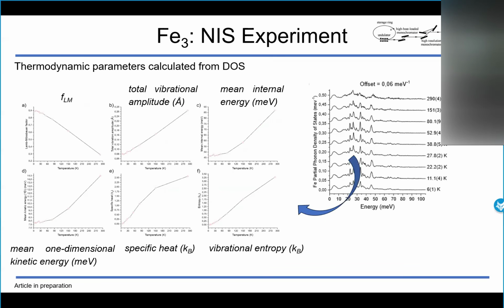And then, from the density of states, we could also calculate a number of thermodynamic parameters, like the total vibrational amplitude, the specific heat, the vibrational entropy, or also the F factor, the Lamb-Mössbauer factor, which is theoretically determined more reliably with this calculation than with the common calculation based on Mössbauer spectroscopy, as here the recoil fraction or the sample thickness is not present in the calculations.